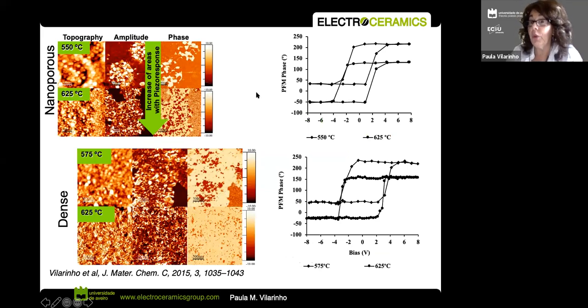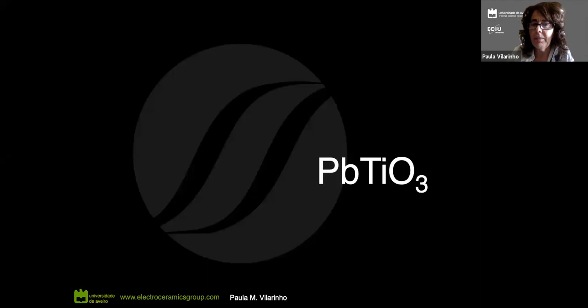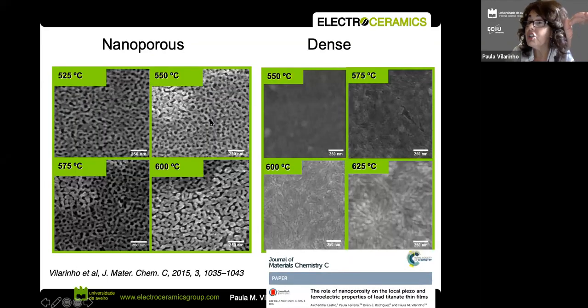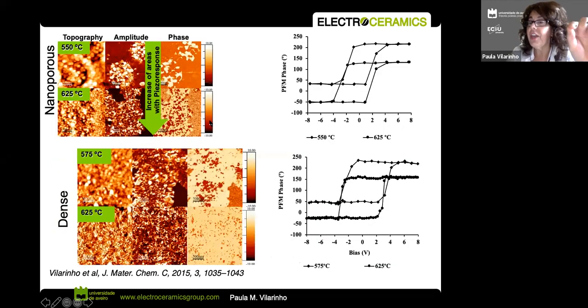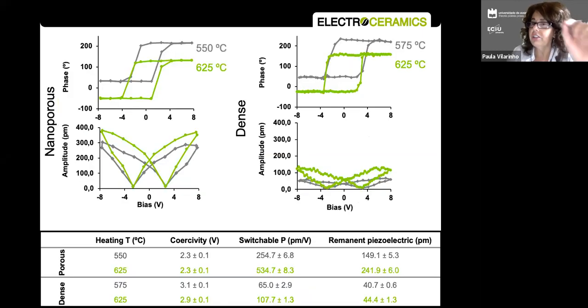These are not simulations. So what is represented here is nanoporous materials, and here dense films, in this case also lead titanate. And what is represented here is atomic force microscopy, local piezo force microscopy, in which we locally measure the switching of the polarization. And what is represented here is that for the porous materials it was much easier to switch, and also we were able to switch for a much longer time. So really the nanoporosity, and when I'm talking about nanoporosity, you can see here, they are really, really small, something like 20 nanometers, sometimes 10 nanometers, sometimes 30 nanometers, they indeed facilitate the switching because locally they create high fields.